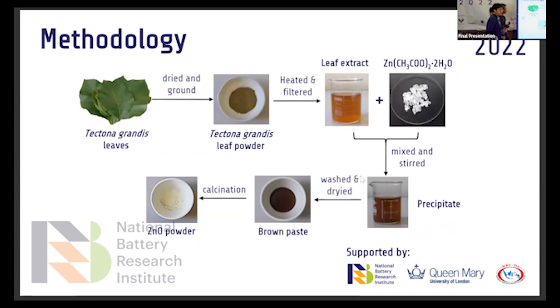And then when you do this, there are several processes, and you mix with the leaf extraction. What is the temperature when you do the calcination, and how long does the precipitation take? The calcination temperature is 500 Celsius, for 19 hours. 19 hours, in which temperature? 500. Okay.